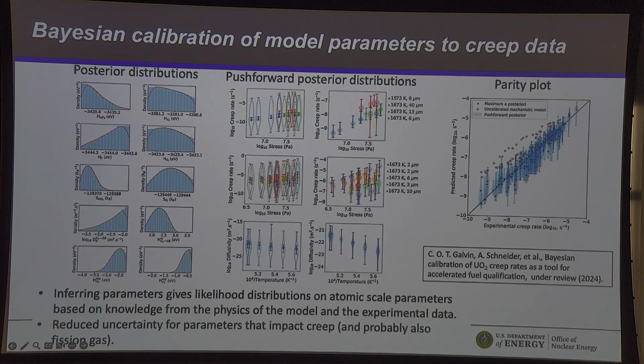The original model, let's see if I get that right, yeah, the red points here, and this is the parity plot, so predicted versus experiments. Not too bad, but they're off. The perfect result here is the diagonal line. When we do the uncertainty quantification and Bayesian calibration, we can get a much better result, and we can get those results with a predicted uncertainty, which again is important for answering qualification questions.